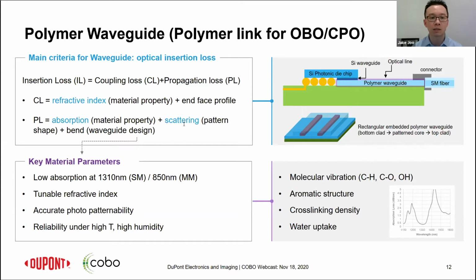Same goes for scattering. If the waveguide has some surface roughness within the pattern structures, you may end up leaking the light. So based on this basic fundamental, what a company like DuPont is doing is trying to identify the material that has the lowest absorption at 1310 nanometers for single mode, or even 850 for multi-mode. We also need to tune the refractive index based on the material composition to meet the target requirement. We also need to make sure that these lines or photo pattern structures are consistent with each other across the whole area. It also needs to withstand all the reflow that we would expect with the other processing it needs to go through.